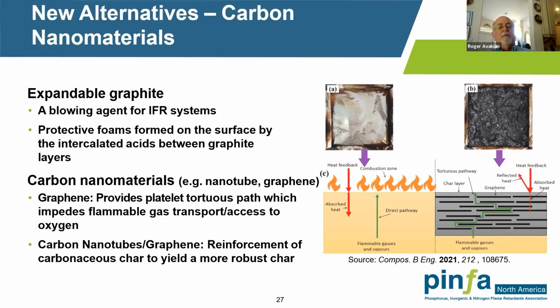Some other carbon nanomaterials that are being looked at and have been used, and there's literature on that, are carbon nanotubes as well as graphene. Typically, the graphene provides a platelet-like tortuous path, again a barrier for oxygen ingress, or for flammable decomposition products escaping and continuing to burn. It also tends to reinforce the char layer.